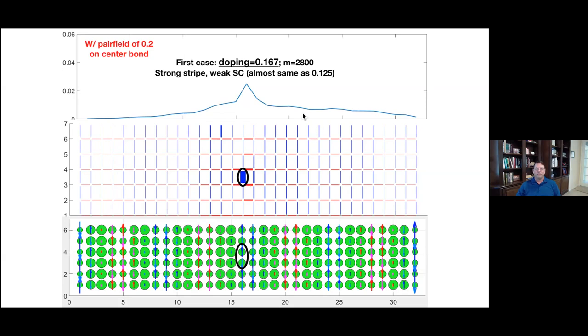Okay. And so here's a system with stripes and a moderate level of superconducting response. It's asymmetric. You see a weaker response on the left and a stronger response on the right. So again, it looks like we have these competing states that are fighting with each other. They look very similar, but they have different responses. And that's the calculation just with this pair field on the center.